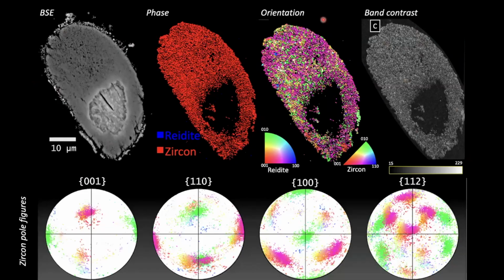So from this orientation map, we get pole figures for zircon. And you might be able to see that there are maybe what looks like 3 clusters on the 110 and the 001. So I would say this is strongly systematically oriented granular zircon. And then I did the same thing for the other grain. So here's that other grain.